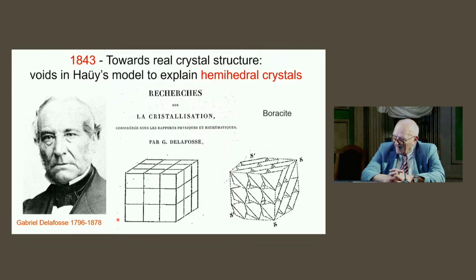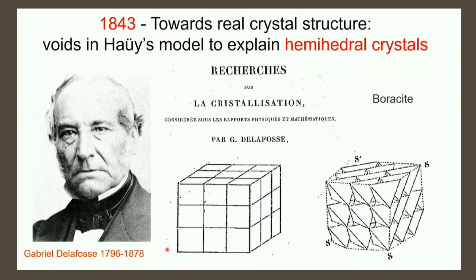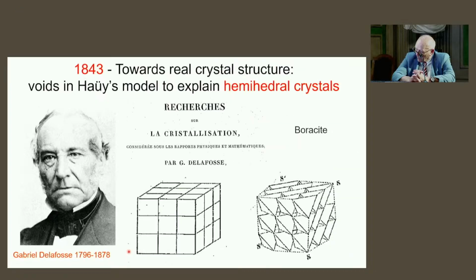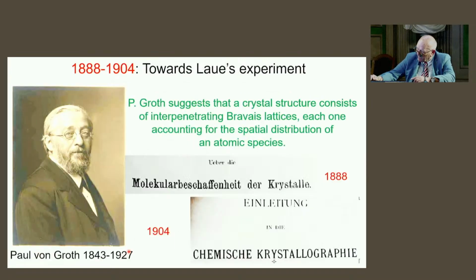Well, I already mentioned that Haüy's theory couldn't explain hemihedral crystals because Haüy's model is centrosymmetric. In 1843, Gabriel Delafosse proposed a model. I show you the model for the mineral boracite, supposing that the crystal structure is based on a packing of tetrahedra. And for the first time, there are voids, because in Haüy's model there are no voids in the crystal structure, and it is not centrosymmetric. Okay, and so this problem that couldn't be explained by Haüy's theory was explained.